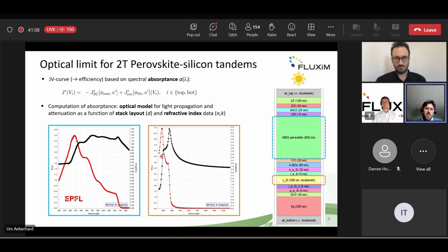You can see here the n and k values for the wide-band gap perovskite. This is for a standard triple cation mixed halide perovskite from EPFL, and then the silicon refractive index data. So we now compute the short circuit current and the radiative dark current based on the absorptions that we get from this data.